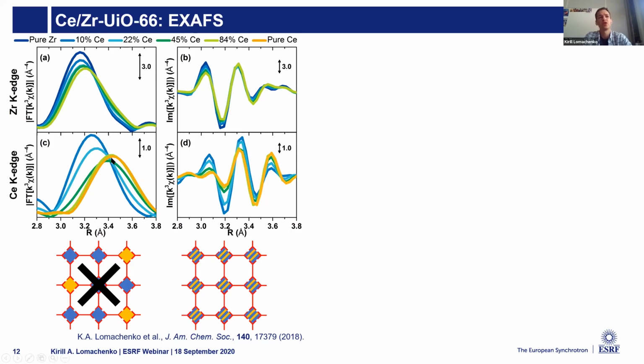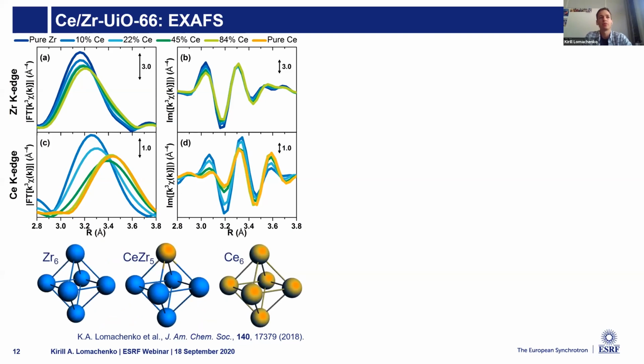Looking at cerium K-edge, where we have a minimum of intensity for intermediate loading materials, it's plausible to suggest that we have the following picture: predominantly three types of cornerstones in the materials, so pure cerium, pure zirconium, and cerium-zirconium 5.